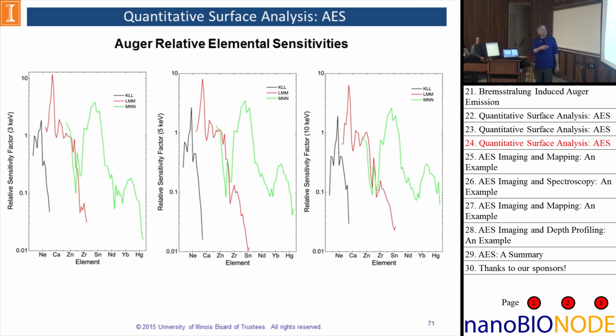But we can play with the electron beam energy, and so we go from 3 to 10 keV to enhance the sensitivity of some of these heavier elements. But all is not lost. Even though a lot of the elements have a low sensitivity, we can see a lot of them. We do drop out when we get to the higher Z elements. And so if you get to something like gold, our limit of detection will be in the several atomic % range.